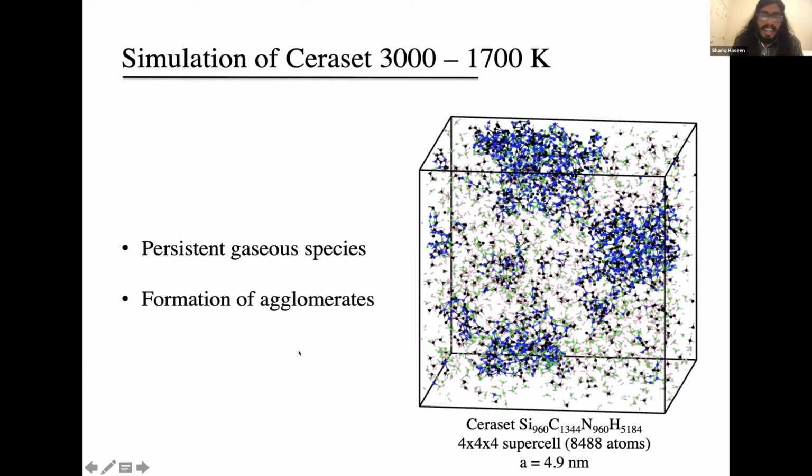So now, after some long time at 3000 Kelvin, we have the structure on the right. And you can see now all these ammonia molecules that have formed. You can see methane too, present in lesser quantity, and it is a bit harder to see, but you could even find the hydrogen there, and they're quite small. So we look at what happens to the structure when it cools down, because we want to see what kind of resulting structures may form, if any form at all.